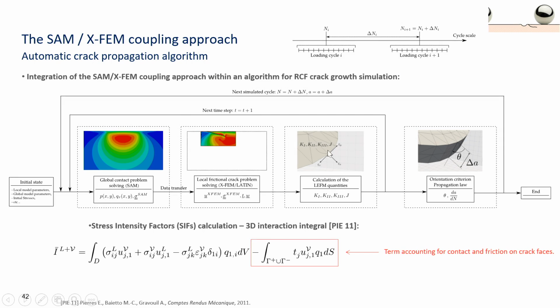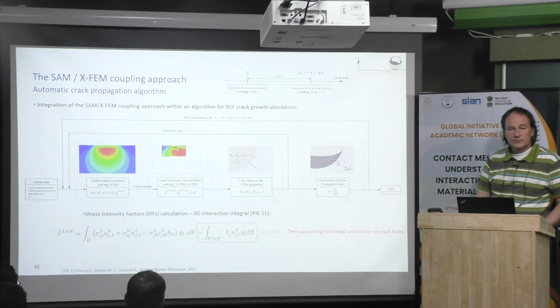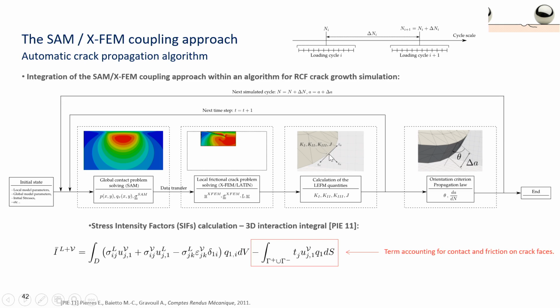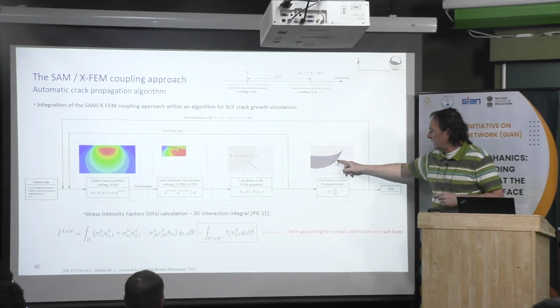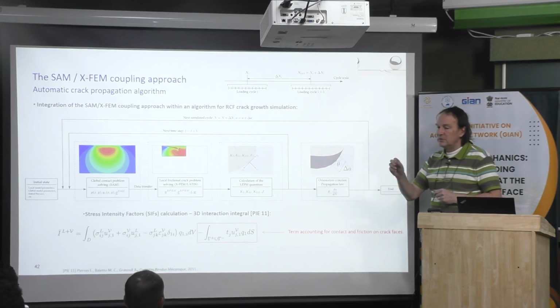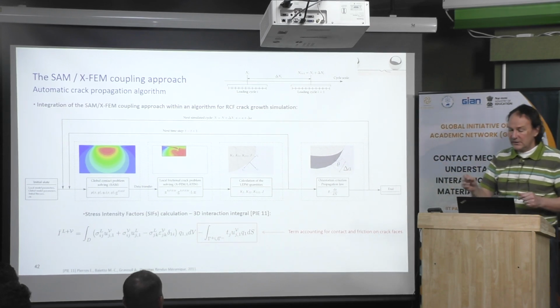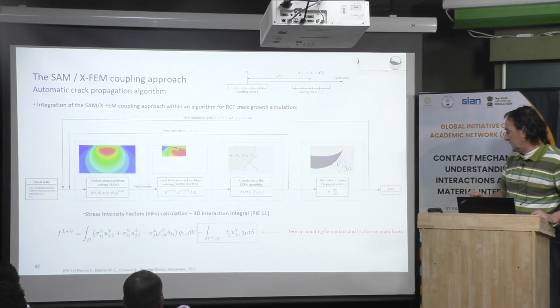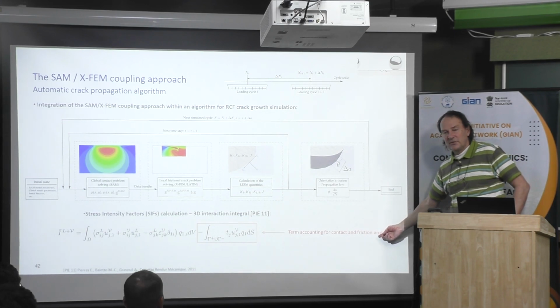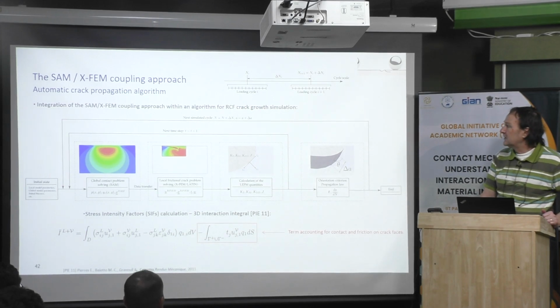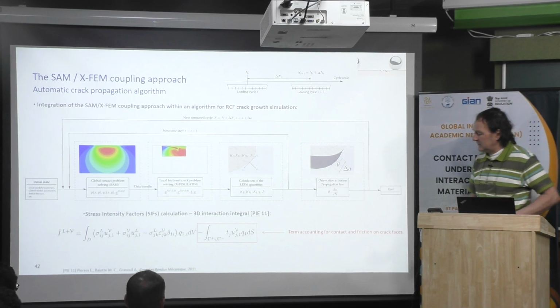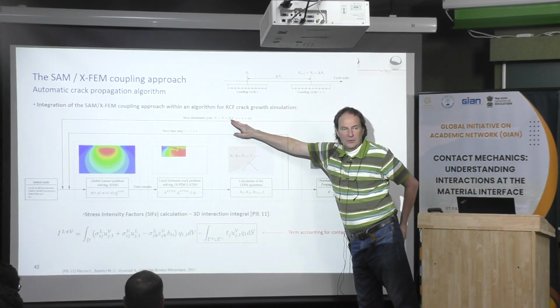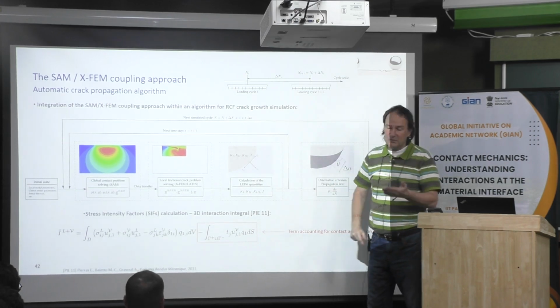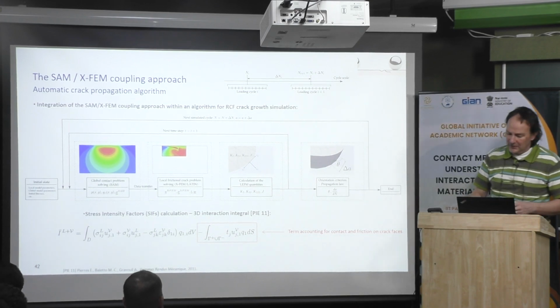Then when you have that, you can calculate the stress intensity factor, mode 1, mode 2, mode 3. And then if you have a crack propagation model, you can calculate the direction in which the crack will propagate and how long per cycle. Okay. Then theta means the direction of the crack, and delta a means the increase of the crack length cycle after cycle. And there is also a term to account for the friction between the crack faces, because we do consider interaction between the two faces of the crack. And so you can see that we use a jump cycle procedure. We do not have to simulate each cycle, because if it is only 10 nanometers of propagation, you can save a lot of time doing that.